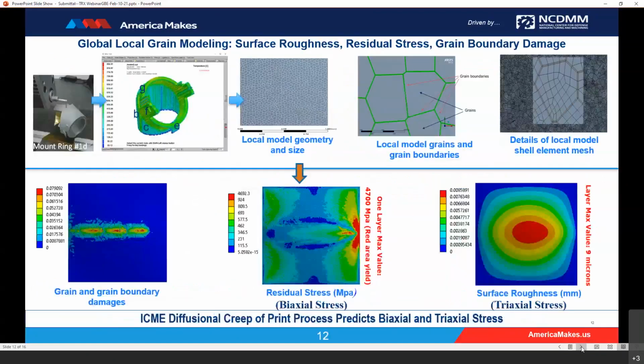What we're trying to emphasize is that this collection of modules allows you to see each component of the process and then optimize based on that individual visualization. This table brings together not only the global-local analysis of the problem, but uses global-local to identify the impact of crack propagation and surface roughness. The local model is a finite element model which is augmented by our TRX crack code, which effectively uses a multi-axis remaining creep ductility approach to predict the growth of voids and precipitates in the microstructural grain boundary structure.